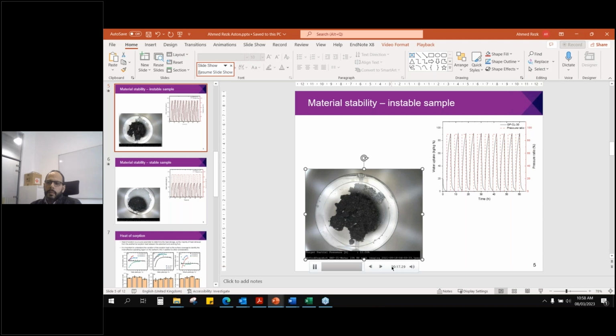When we look at the applicability of this material, it is not really very applicable, because when we pack it into the adsorption bed, the salt might leave, it will leave the matrix, and you are left with an empty matrix, and the salt will go everywhere in the machine. So we can't really use this. So this is one of the important features. We can look at the physical stability of the material and whether it is applicable or not.